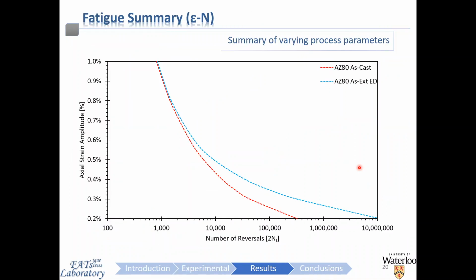So to summarize how one might select the optimum forging condition based on all of this information, we can utilize a number of metrics. Since the fatigue response is the focus here of this particular application, I'll discuss how varying the processing parameters affect the strain control fatigue response. The strain life curve presented here is for both forms of magnesium alloys, cast and extruded. Now we can recall that the extruded material is textured and will exhibit an asymmetric cyclic response. Accordingly, you can see this induces anisotropy in the fatigue life.